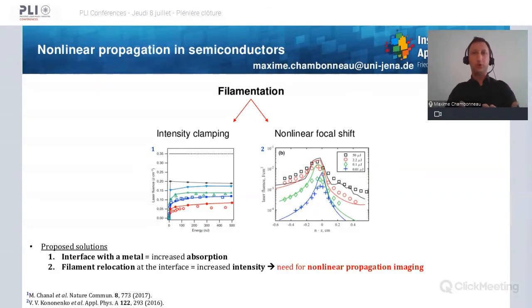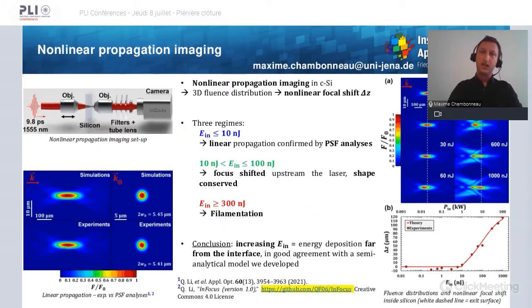But to do so, we need nonlinear propagation imaging. And basically, this is what we did with the setup shown here. We imaged the nonlinear propagation inside silicon. Here you can see it's nothing else than an inverted microscope working in transmission, which allows us to retrieve the 3D fluence distributions, as you can see here on the right, as well as the nonlinear focal shift delta Z as a function of the input pulse energy.